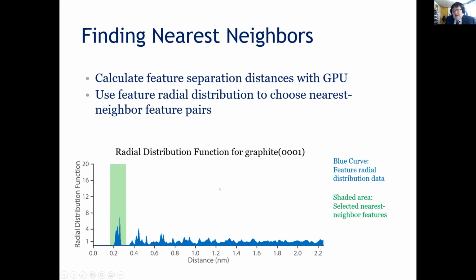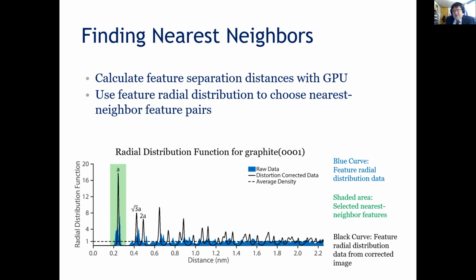With those feature locations, we can determine how their positions are related to each other by example of finding nearest neighbors. So this is a radial distribution function of the feature distances from each other, and there's a big spike at exactly the nearest neighbor distance, so you can identify which features are nearest neighbors. You can see before the distortion correction with the blue data, it still works, but after the distortion correction, it gets much better.